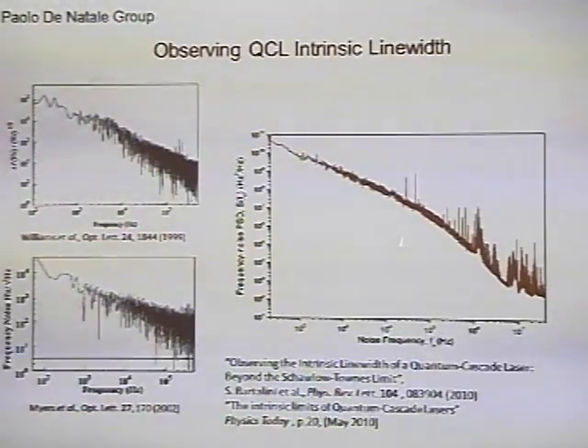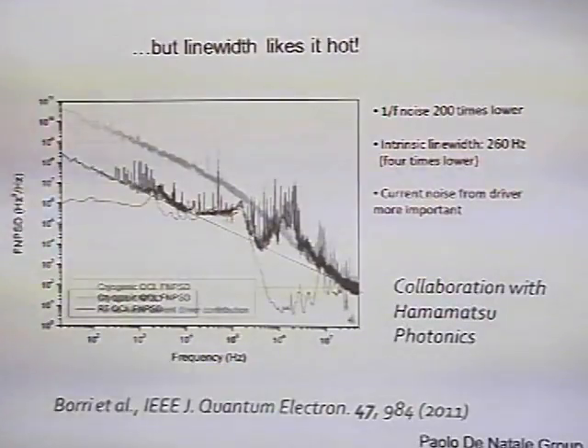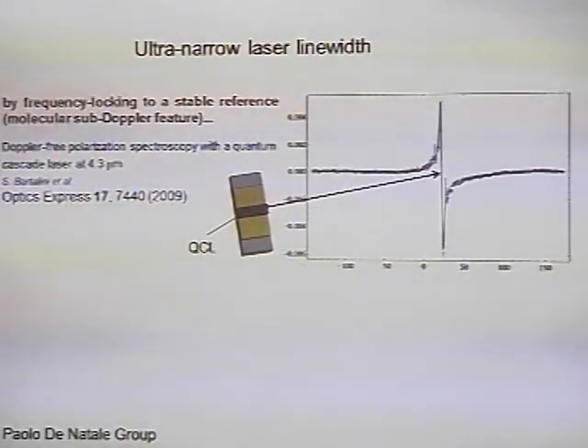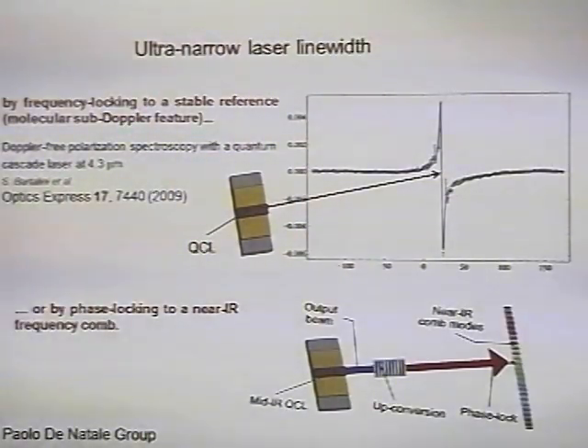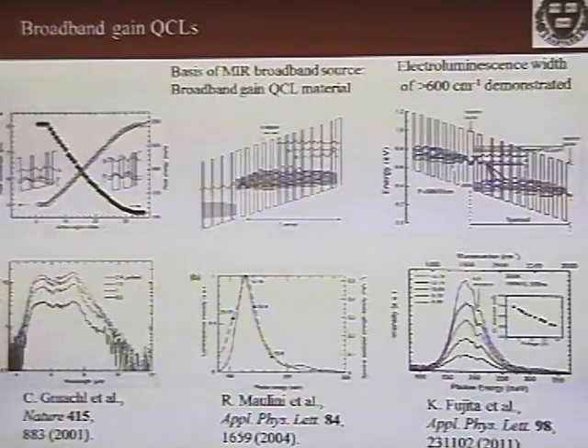At low frequency, you see you're dominated by shot noise, by 1/f noise and so forth. But then as you go to high frequency, you get rid of this 1/f type noise. You see this plateau. And if you scale the actual temperature, the actual power of the laser, you see that this plateau follows Schawlow-Townes. So now they are down to a few hundred hertz, which is very significant. And it's a variant, actually, of Schawlow-Townes. They've done beautiful work on phase locking to a near-infrared frequency comb. So there's not time to go into this.